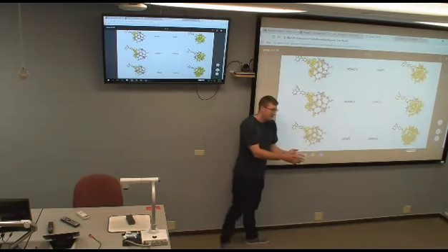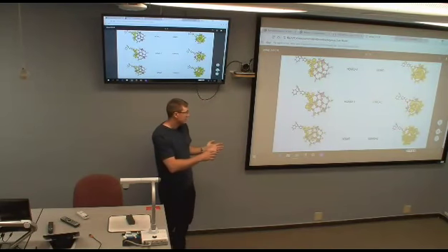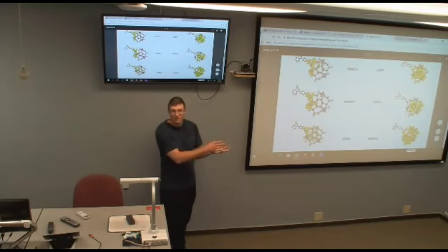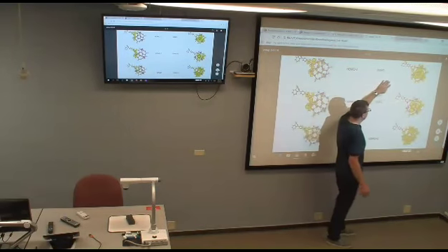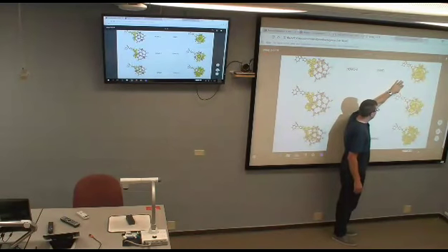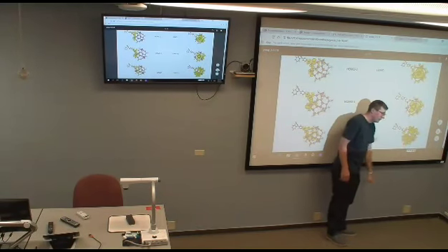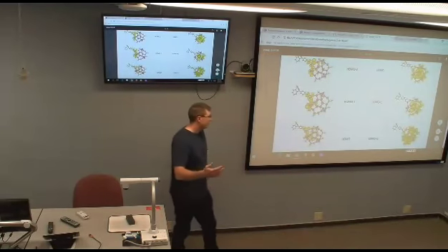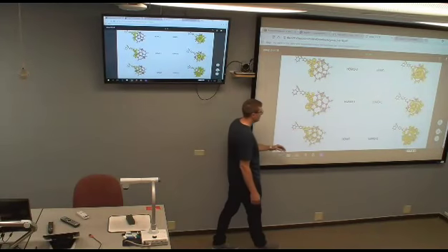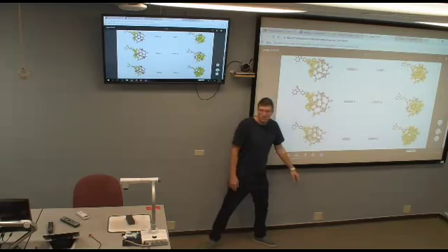So right on that valence band edge, we should have any type of charge relaxation moving towards this part of the system. Whereas when you're looking at the orbitals above the band gap, you see that they're still primarily localized on the quantum dot. So something being excited optically is going to come back down and ideally be somewhat separated from where the hole localization is taking place.